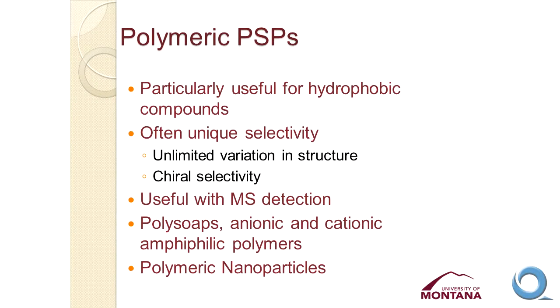So we've been looking at ways to develop new materials which will overcome some of these limitations and provide additional separation selectivity. And we have focused on polymeric materials as the materials to use for pseudostationary phases. We have found that they are particularly useful for the separation of hydrophobic compounds because we can add organic solvents and optimize the retention factor. We found that they often give us unique selectivity because we can vary the structure of the polymer without worrying about its aggregation properties, whether or not it will form micelles.